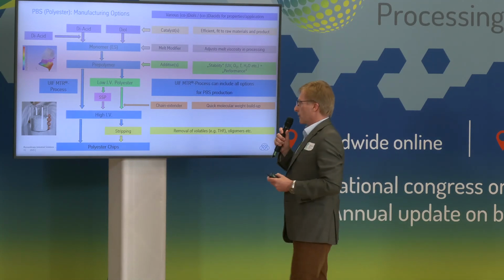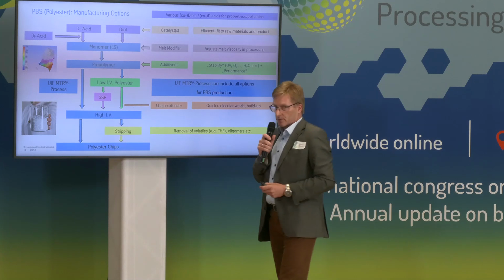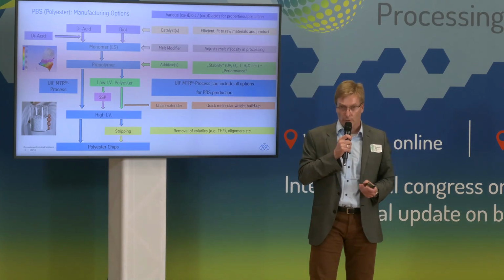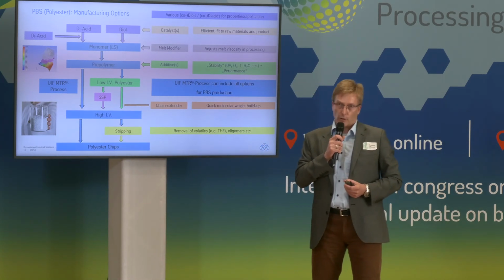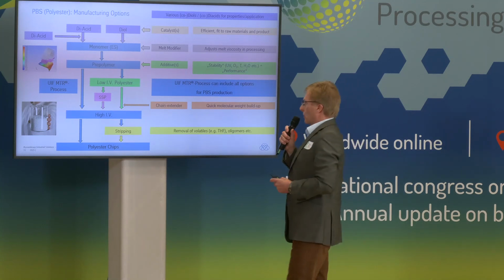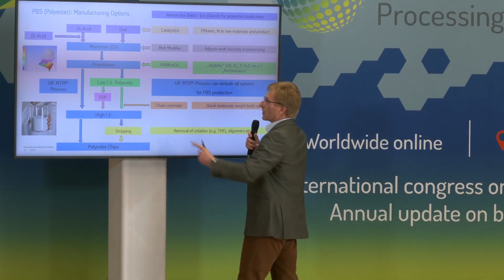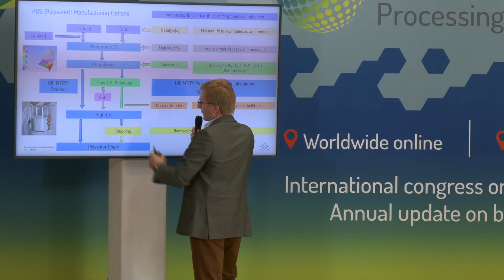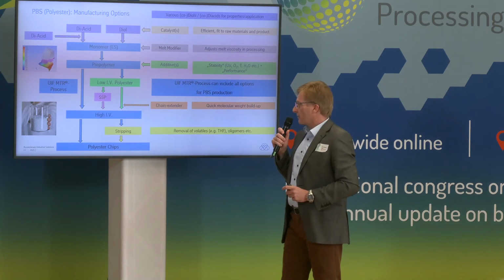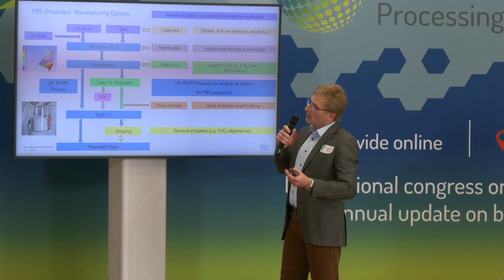What you could do alternatively is introduce some chain extenders, highly reactive chemical compounds, which help you to build up the molecular weight quickly. This is no longer required. With our MTR process, you can go directly from the pre-polymer to the high IV viscosity material.